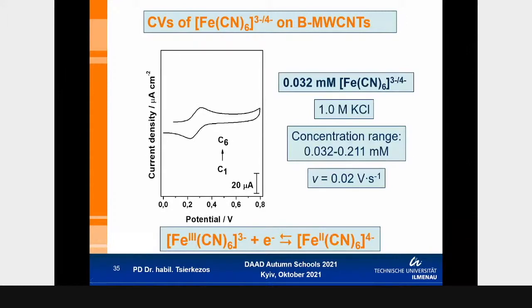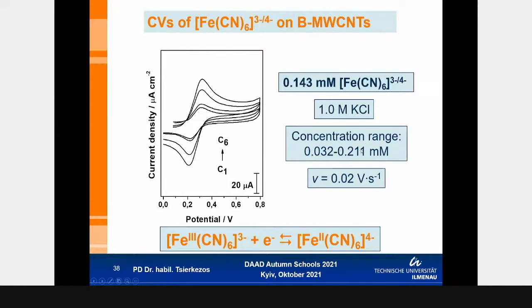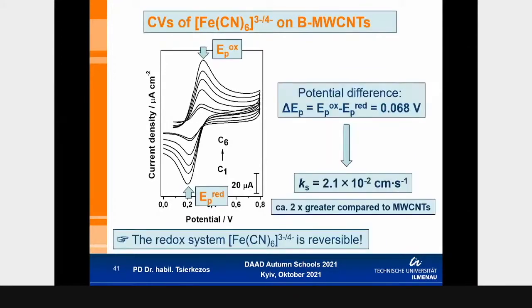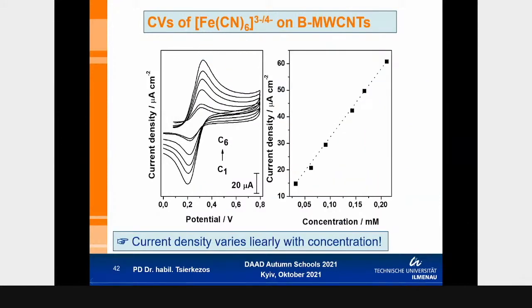I have done the same with different concentrations of the redox system in this range, and I have observed also that with the increase of the concentration, the current increases. So we have a linear variation of the current with the concentration. The system is completely reversible, and we have a huge rate of electron transfer. And compared, for example, boron nanotubes to the pristine without doping, we have found that with doping of the carbon nanotubes, the kinetics of the system increase. Okay, this is the linear variation of the concentration with the current.